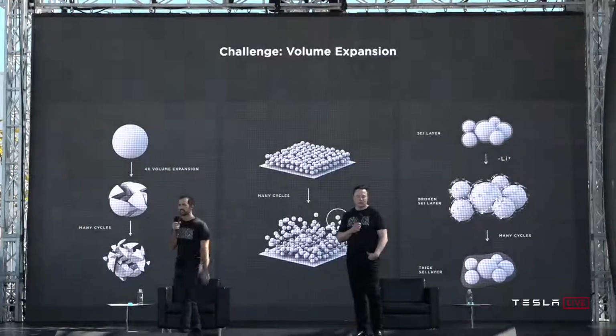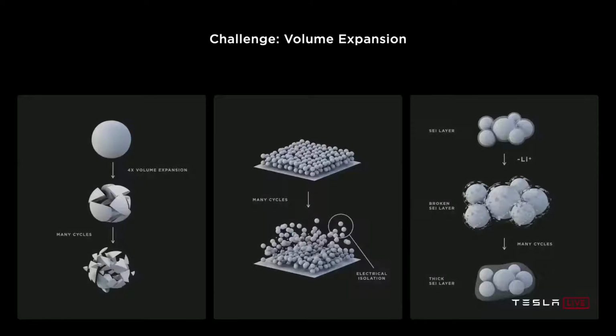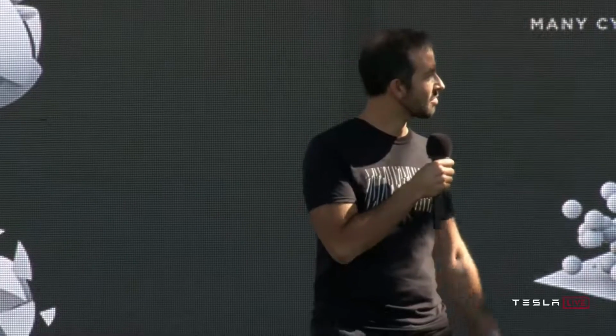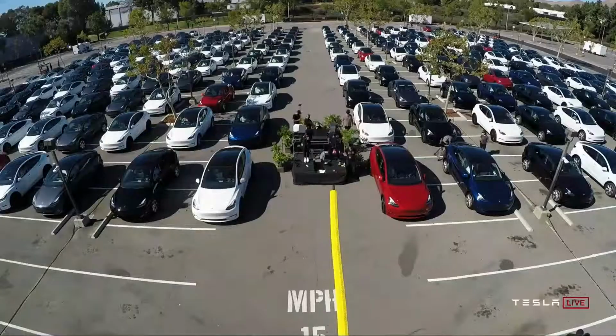The main reason is that the challenge with silicon is that it expands 4x when fully charged with lithium. And basically, all of that expansion stress makes the particles start cracking. They start electrically isolating. You lose capacity. The energy retention of the battery starts to fade. And it also gums up with a passivation layer that has to keep reforming as the particles expand. Basically, with silicon, the cookie crumbles and gets gooey. That's basically what happens. Good analogy.